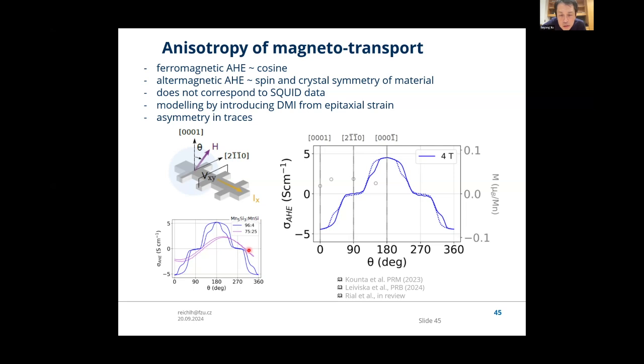Helena, can I ask a question? Yes. When you rotate the angle, is it satisfied that at all angles your current, your Hall voltage and your magnetic field are perpendicular to each other? It's the orientation of the current and the magnetic order vector. So this is not the magnetic field, because you have to assume what the magnetic field does to the spins, and then what it does to the spins matters for the voltage which you measure in the anomalous Hall effect. The magnetic field matters only for the ordinary part, the cosine-like part. The rest depends on the orientation of the magnetic order vector. So I see. I have to understand how the magnetic field influences the magnetic order.